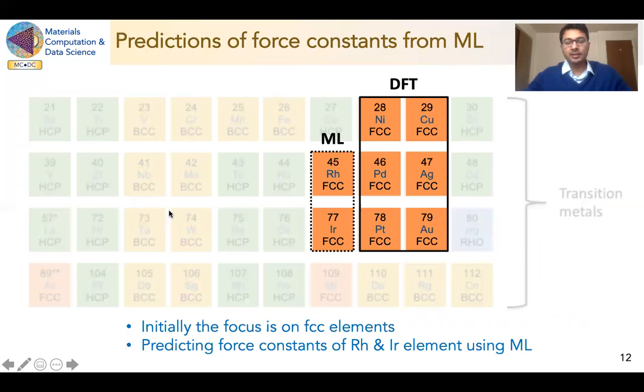Transferable force constants give us the advantage to develop the machine learning framework, which is our goal. As we know, the vibration entropy can be predicted from the force constants of all the bonds. So instead of predicting vibrational entropy, we are actually predicting the force constants of the bonds, and from there we will calculate the vibration entropy. So our idea is to make a database of force constants of a few elements, and then using a machine learning framework, predict the force constants of other elements for which data is not available. So to test this idea, we first focus on the FCC elements, and our idea is to train our model on these 6 elements and then predict the force constants of rhodium and iridium.